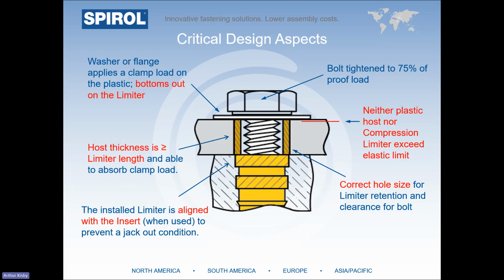Ideally, we want some plastic compression of the plastic, as it does tend to relax over time, and we wouldn't want the plastic host to shift up and down along the length of the limiter. In some instances, achieving this may be difficult, especially in cases where the plastic host is on the thinner side and your mold can't hold super tight tolerances. So we implore you to consult with us so we can provide more complex recommendations when required.